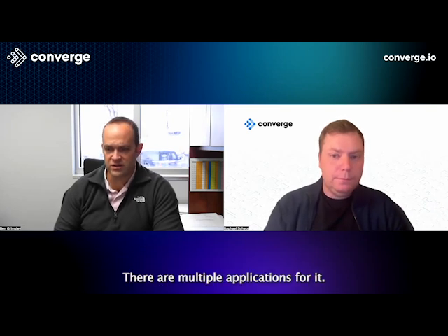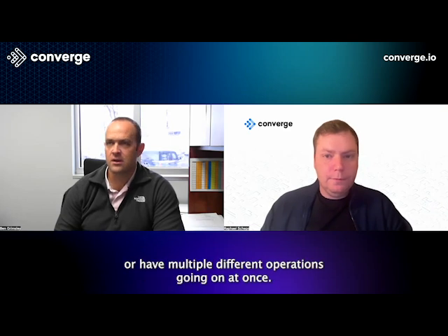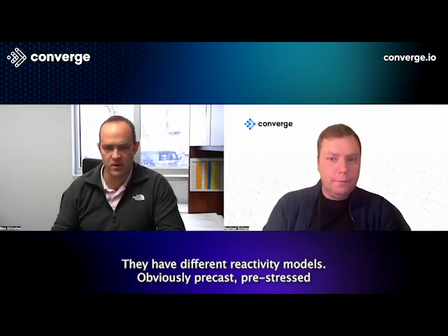There are multiple applications for it. On the vast majority of data center sites that I've worked on, we've had on-site ready mix or precast, multiple different operations going on at once. When you're operating a portable batch plant, you're shifting between precast concrete, pre-stressed concrete, and flatwork concrete. They're designed drastically different. They have different reactivity models. Precast and pre-stress are typically trying to strip a bed somewhere in the 10 to 12 hour range, versus more slowly and evenly growing flat work or cast-in-place models.